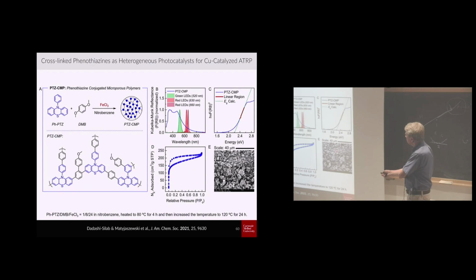You have particles of a size, primary particles, maybe sub-micron, and it's very easy to filter, remove it. You have a very large surface area, around 500 square meters per gram. And if you look at this band gap, it would really correspond to 550 nanometers, which you could see really overlaps with green light and also with red light. So now you can use green light, red light under heterogeneous conditions with a tiny amount of copper. So without copper, you have no control.